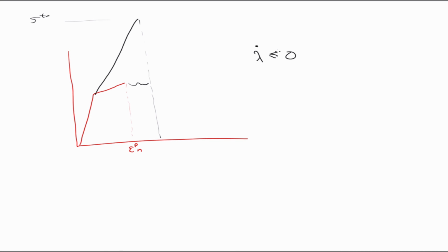This occurs a lot in viscoplasticity and other things where you can have a vast amount of change in the yield surface over a step. Even if your if statement includes the previous value and you say, okay, I'm going to treat it like it's elastic, because of your rate hardening the thing jumps up so high over one step that once you evaluate where you really are, you could be below it. And then you say, oh, I'm not really plastic.